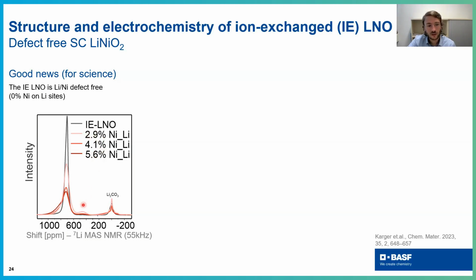And if you look at the NMR signal at around 700 ppm here, then you see that this peak is increasing with the decreasing nickel on lithium sites. And the signal is the highest for our ion exchange sample, which is already indicative that we are very low in the nickel and lithium exchange here. Also, XRD confirms that we have no nickel on lithium sites.